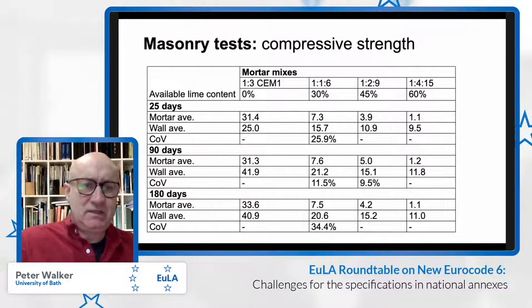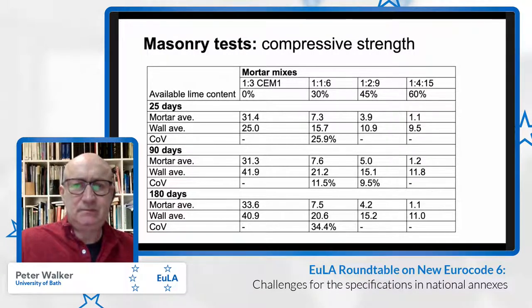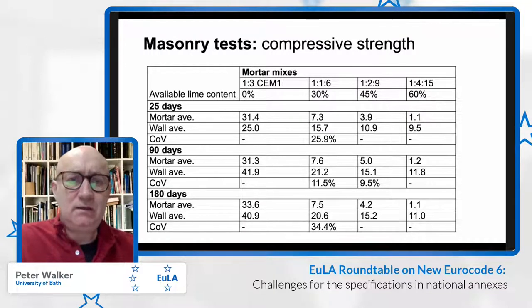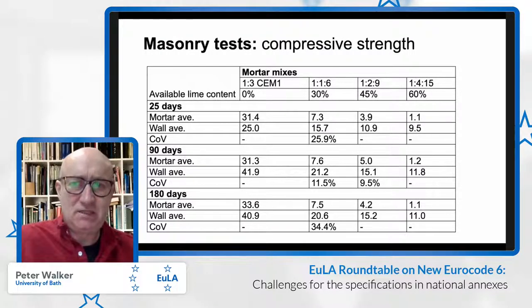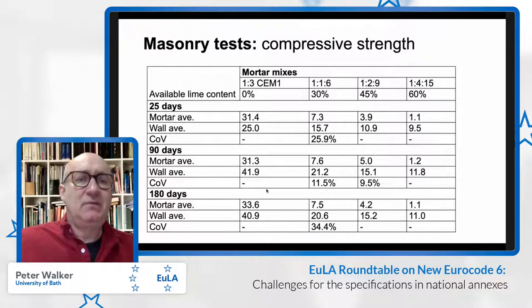Moving on to the masonry tests, first of all, presenting the short-term static compressive strength tests. Here we have results at different ages, at 25 days, 90 days, and 180 days for the different mortar mixes, and then the wall compressive strengths. So we have the mortar strengths for each age first, and then the wall average strengths.